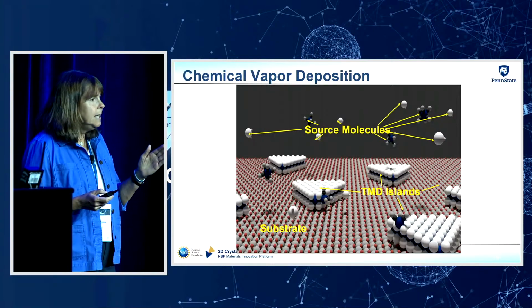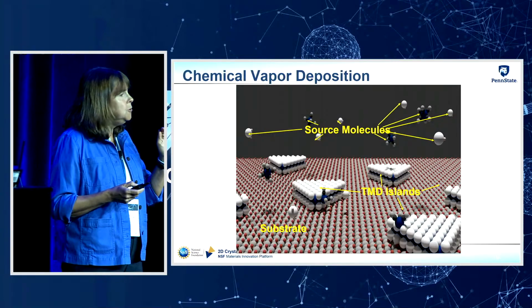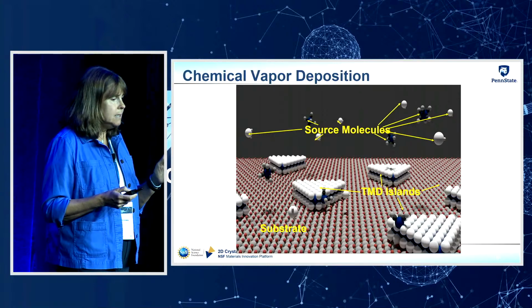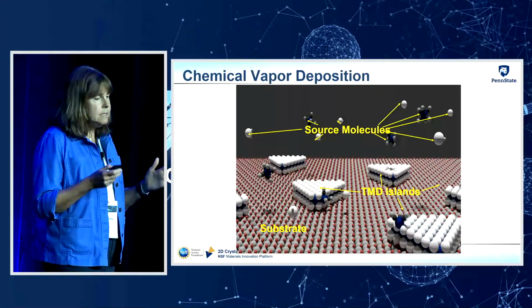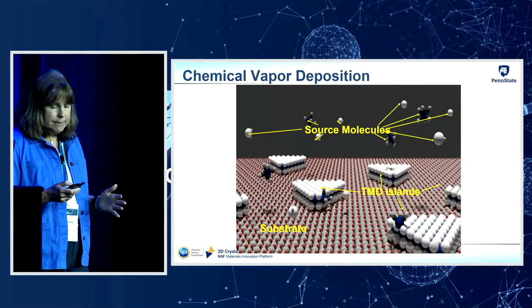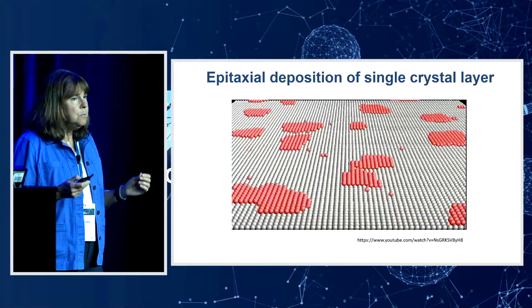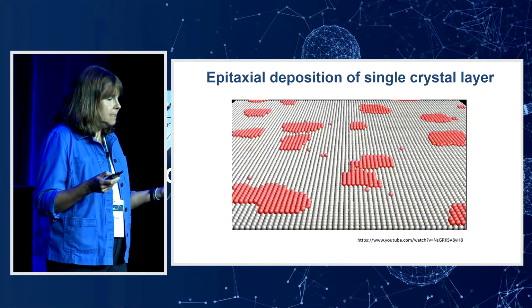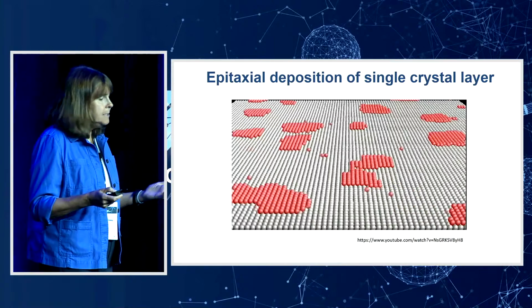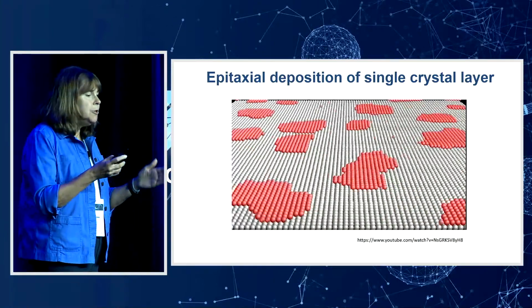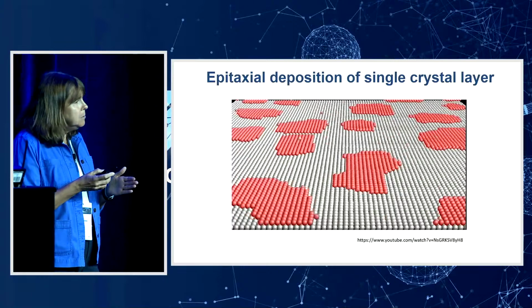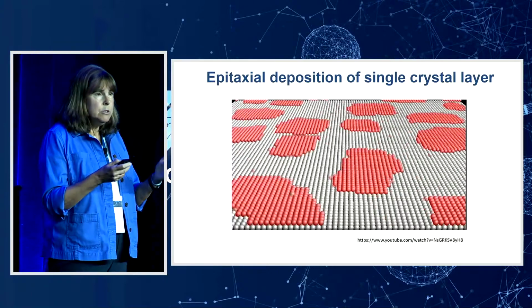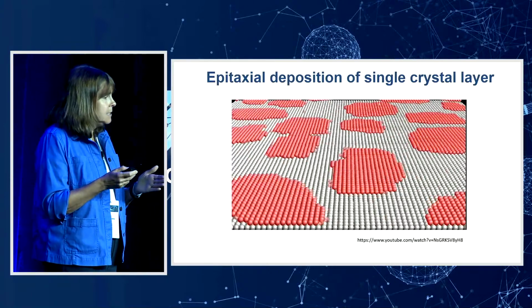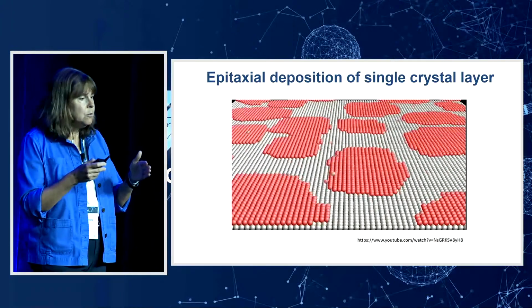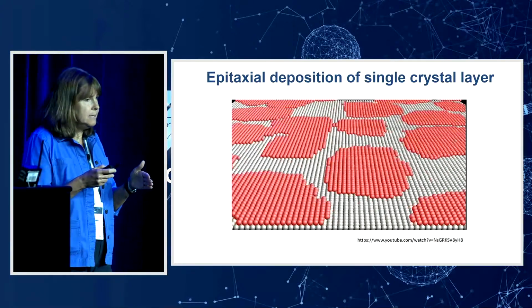Now, in order to get a film that has few grain boundaries or other defects, we need all of these islands to be well aligned on the substrate. And to do that, we use a process called epitaxy. So in the case of epitaxy, you're using a substrate that has a similar crystal structure, similar spacing of atoms, and you're using that to template the orientation of the film that you're depositing, right?